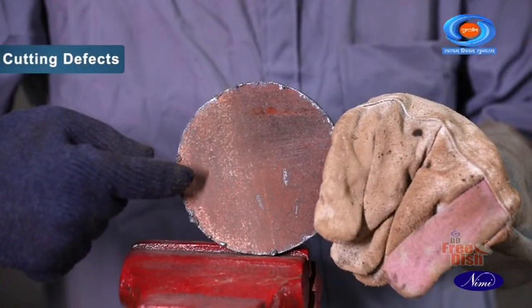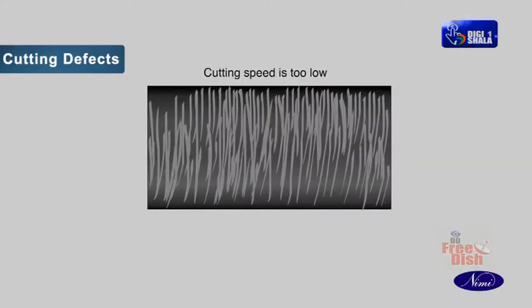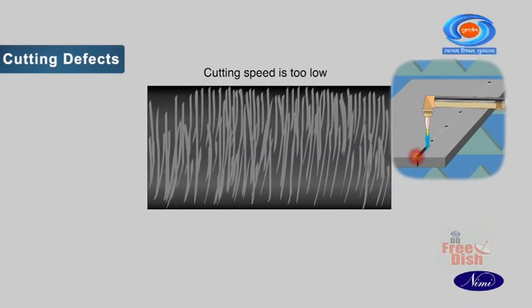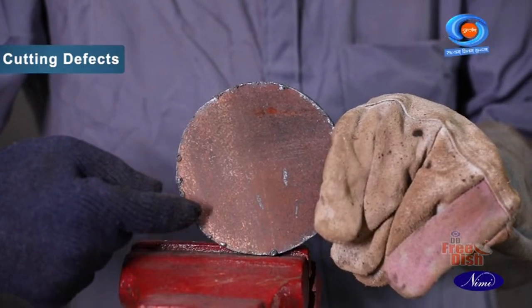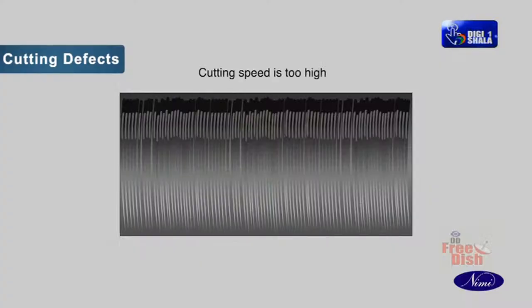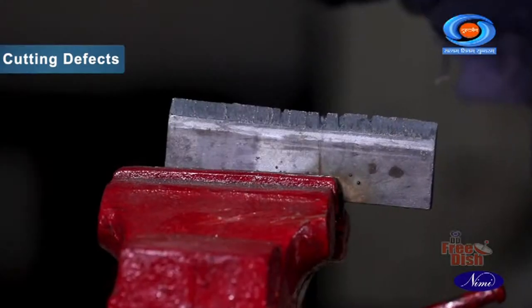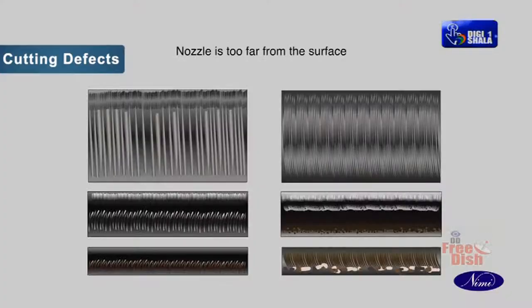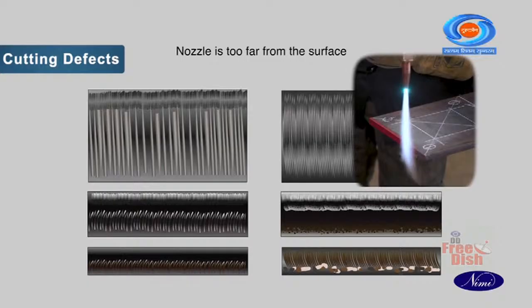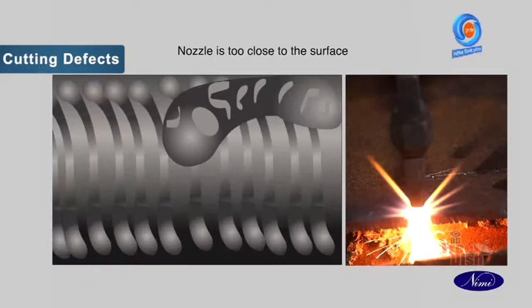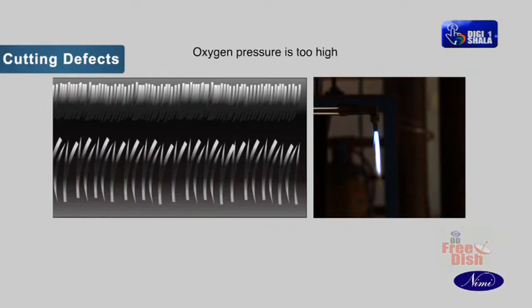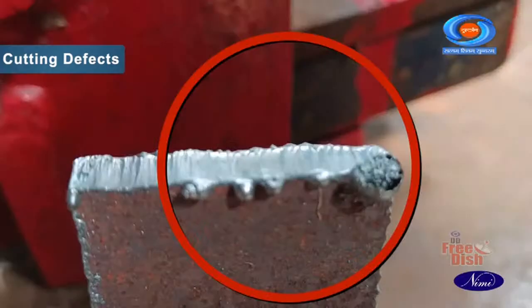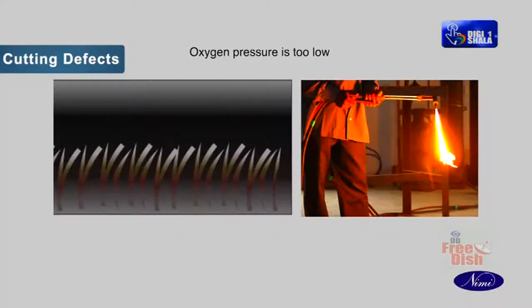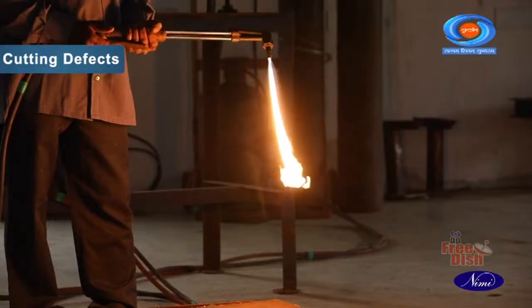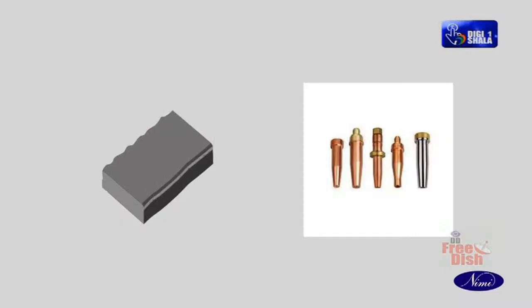Let us see some common causes of oxyacetylene cutting deficiencies: cutting speed is too low, cutting speed is too high, nozzle is too far from the surface, nozzle is too close to the surface, oxygen pressure is too high, oxygen pressure is too low, excessive preheat flame, or incorrect nozzle.